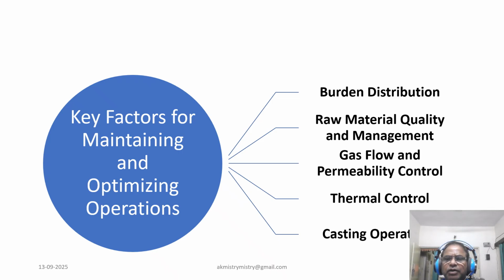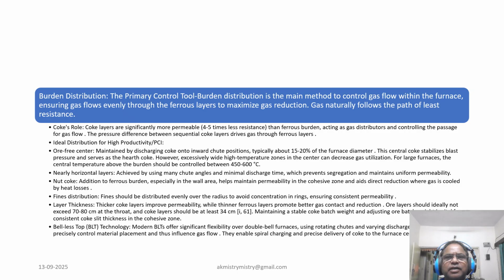Now, coming to our topics one by one, let's start with burden distribution, which is considered the primary control tool. Its main purpose is to manage gas flow within the furnace, ensuring that gas flows evenly through the ferrous layer to maximize reduction, and this is how we can optimize our fuel rate. Remember, gas naturally follows the path of least resistance, and that is well known to all operators. Here is where coke plays a crucial role. Coke layers are significantly more permeable, offering about 4 to 5 times less resistance to gas flow than the ferrous burden, and this makes coke an excellent gas distributor, creating controlled passages for the gas flow. And the pressure difference between sequential coke layers is what drives the gas efficiently also through the denser ferrous layer.